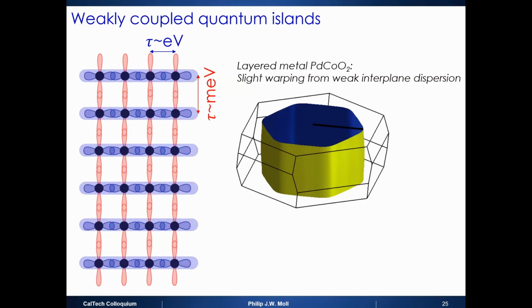Now, the whole idea of a Fermi surface breaks down even though you're in a limit of many, many Fermi momenta in the plane. But because the problem is anisotropic, you really have to think about this as a delocalized quantum island, and the transport along this really is a transport of this delocalized state hopping into the next plane. It's kind of going into the next story of a building, okay? And you can see that this must be the case because the semi-classical transport in the C direction is given by the warping of the cylinder.